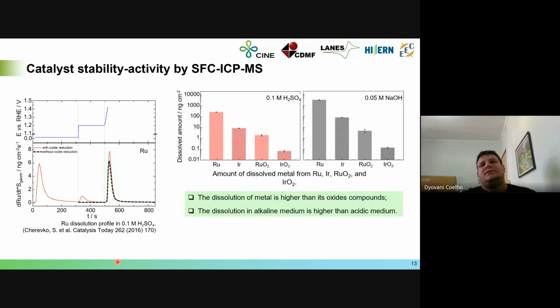And that was verified with other kinds of catalysts, such as iridium, ruthenium oxide, and iridium oxide. And they observed that the dissolution of the metal is higher than that of its oxide compound, as you can see here. And the dissolution in alkaline medium is higher than in acidic medium. Actually, the dissolution in alkaline medium is at least one order of magnitude higher than in acidic medium. This explains, in part, why this catalyst is a benchmark for PEM water electrolyzers, but not for AEM water electrolyzers, at least yet.